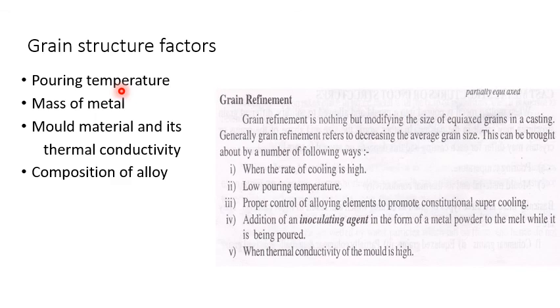The mass of the metal also matters. Whenever we pour a large amount of metal, there is no time for solidification, so we can get a fine grain size. As for the mold material and its thermal conductivity, if the mold material has a high thermal conductivity, the heat flows readily, and the grains will not grow into larger ones. The composition of the alloy also matters. If there are any intermediate or hard particles present, they will lead to heterogeneous nucleation, the number of nucleation sites will be more, and that leads to equiaxed grains also.